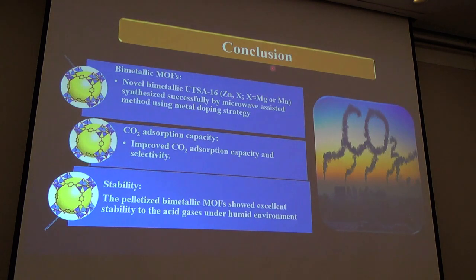Conclusion: novel bimetallic UTSA-16 bimetallic MOFs were successfully synthesized by the microwave method using metal doping strategy. Improved CO2 adsorption capacity and selectivity were observed after secondary metal ion doping. And the pelletized MOF showed excellent stability to acid gases under humid environment.